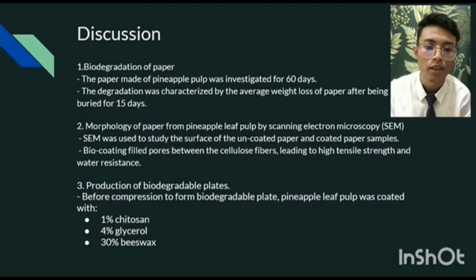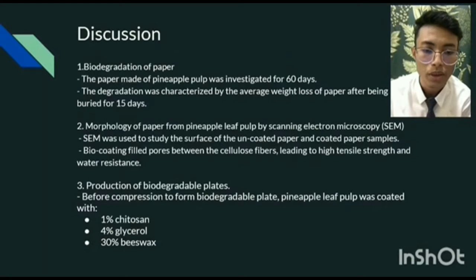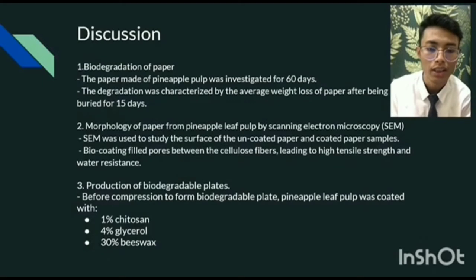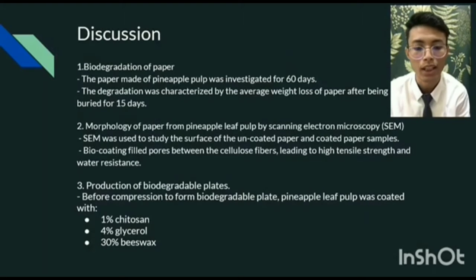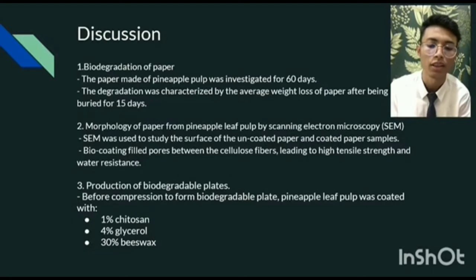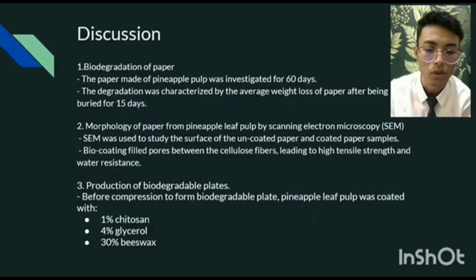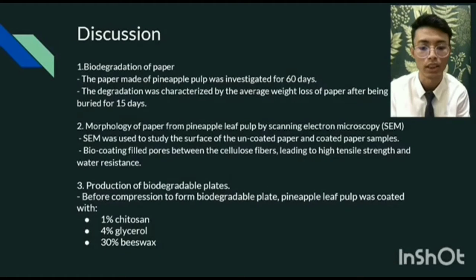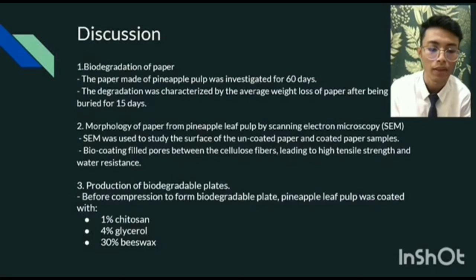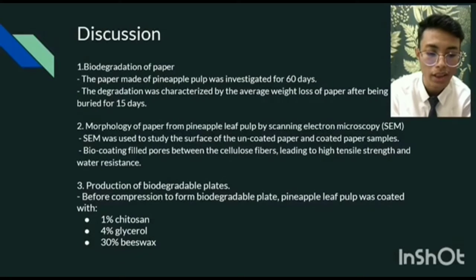They say there was a difference in bio-coated paper with beeswax chitosan. Paper coated after hot pressing with beeswax chitosan solution degraded faster than before hot pressing. It is because after compression, the biocoating solution coated only the paper surface, but when coated before hot pressing, the solution was heated and compressed into the bulk paper, inducing cross-linking that gave resistance to microbial digestion and degradation.